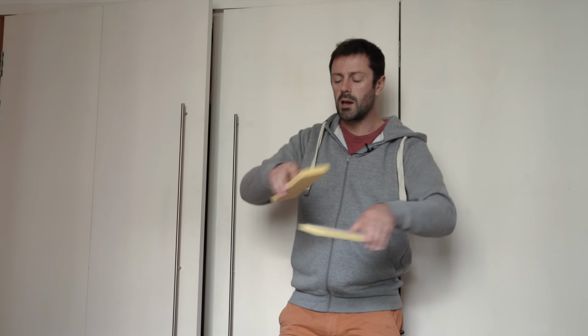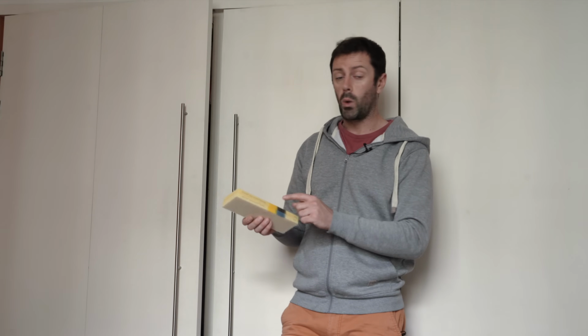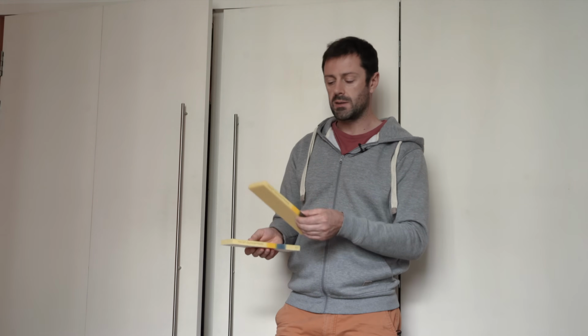The 80s will be around the sides, which require a little bit less compressive strength, and I'm going for a slightly thicker laminate in that area. And then for the floor sections, the lower parts, we're going with a denser M100, so 100 kilograms per cubic meter, and that will give us slightly more compressive strength.